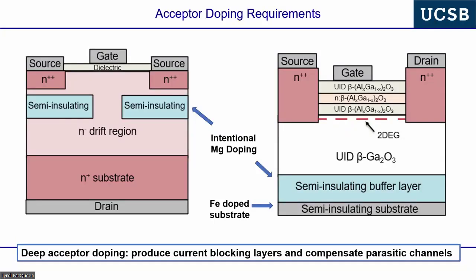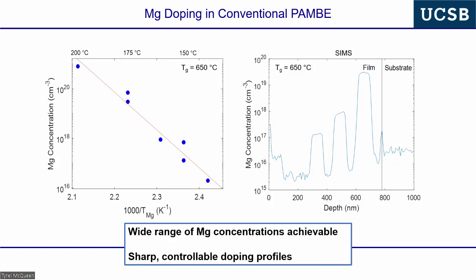And we have a lot of far-out interest also in these acceptor-doped layers. This is an example of what we do in our research. This was grown by my student, and very often we do what are called SIMS stacks. We start with the substrate, grow material, then open a shutter so we have a flux of the intentional dopant, and close the shutter. We are very worried about this concentration. This shows a nice example of controllable magnesium concentration over several orders of magnitude. We're very concerned about this rise profile and this fall profile in the structure, and this is something we do routinely.